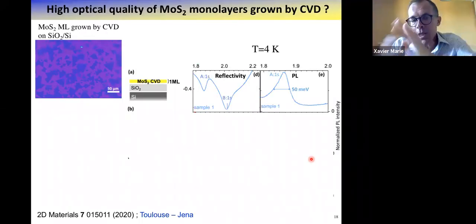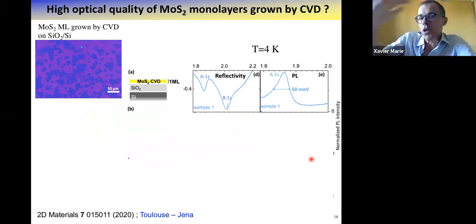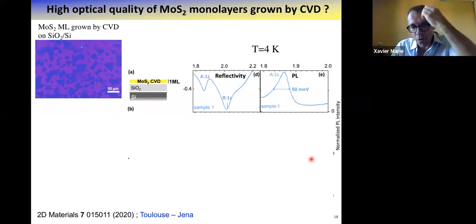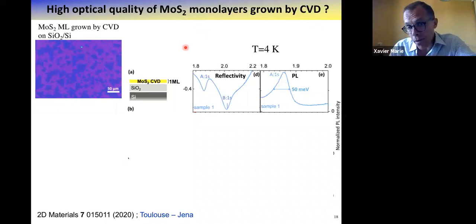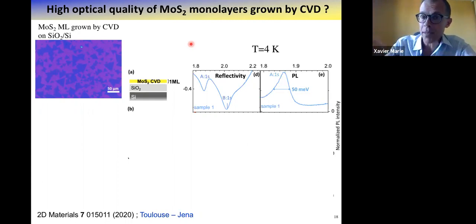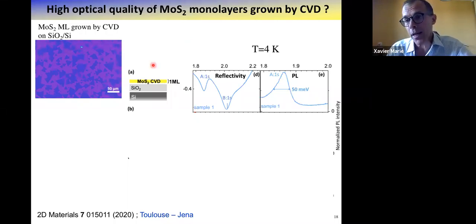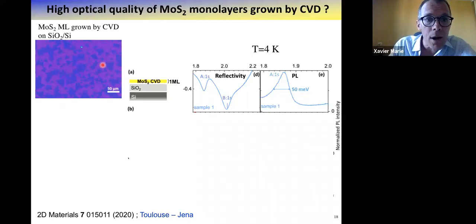Of course, so far I have presented results on exfoliated monolayers, just mechanical exfoliation and transfer. And as you know, many people work on getting much larger area monolayers, and one of the solutions is usually given by CVD monolayers. For many years, as many groups, we have tried to work with CVD monolayers, but with rather disappointing results in terms of photoluminescence or reflectivity characteristics. And for many years, I said that CVD monolayers were of very bad quality, and I was wrong. As I will show here, again, it was a problem of the dielectric environment. Here is an optical image of a CVD layer. Maybe you can recognize the classical triangle corresponding to a monolayer.